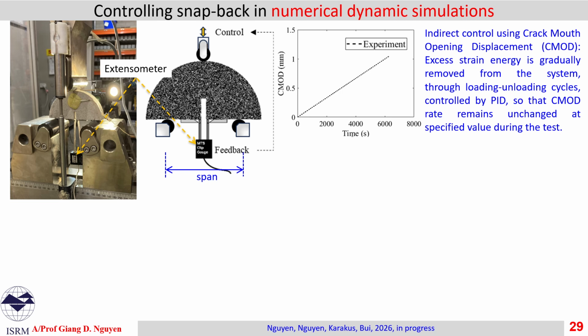We show here more numerical results on three-point bending tests on a semicircular disc specimen, and this is the test result. We use what we have explained earlier, PID control, to control the crack opening. The crack opening rate here, this is test data, is always constant in this case, and as a result, crack opening is a straight line like this. That's it, the results obtained from our test.